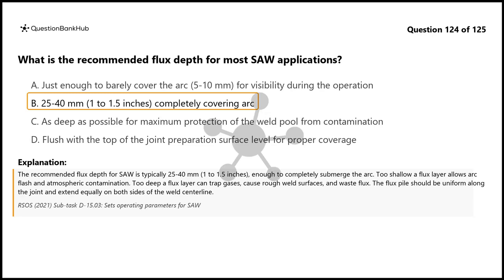Too deep a flux layer can trap gases, cause rough weld surfaces, and waste flux. The flux pile should be uniform along the joint and extend equally on both sides of the weld center line.